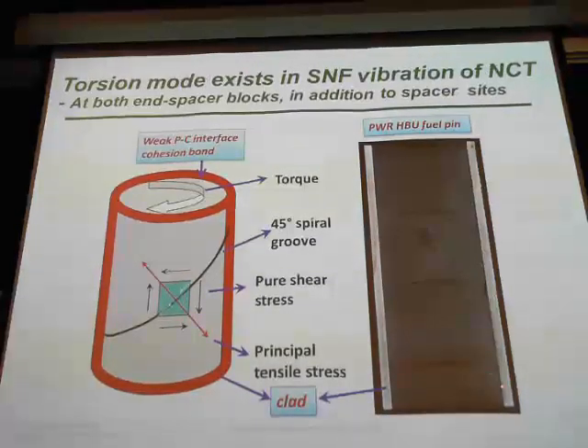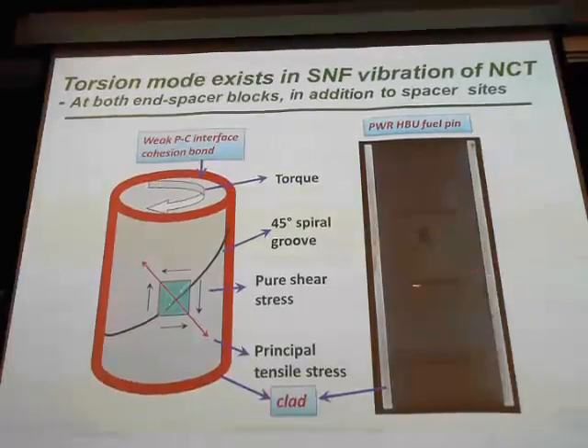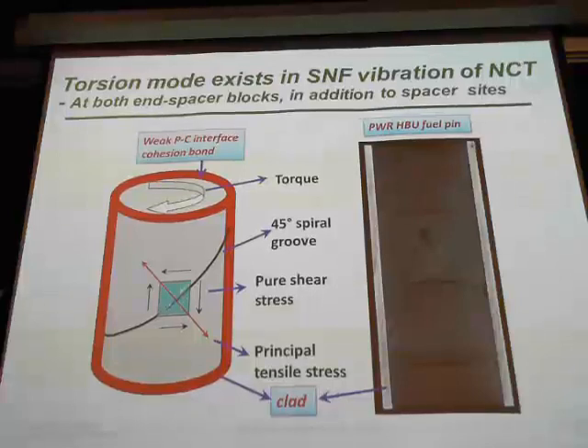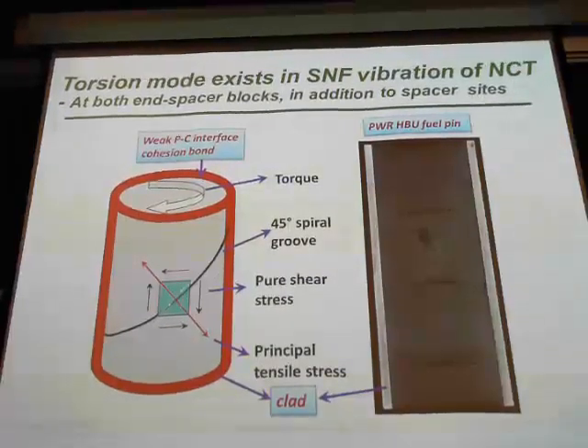But here, see there's contact. So our concept is, we believe at this point there's not too much cohesion bond. A lot of PWR fuel has pressure residual stress, cladding residual stress. So when you apply torque, the fuel doesn't really support; when you bend, the fuel gives support, but when you torque them, the load will only be sustained by the clad. And if you take high burn-up fuel, which has bonded the fuel to the cladding because of fuel swelling, then when you cool it down, does it split open that fuel-cladding bond? I will show you a picture. You're ahead of me. Okay, there's thermal cycle crack. Yes, so the initial bonding by fission gas deposition really is not much left.